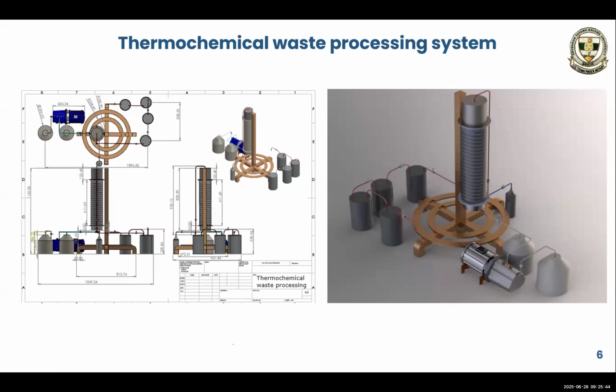hot demineralization, where with this system we charge in the water to demineralize the torrefied biomass while it is still red hot. The inorganic material that normally results in the formation of ash is already excited, and by the time you add water to it, it's quenched directly and leached into the water. Then you've got water which is rich in alkaline metal, which can be utilized for lignin extraction. So this is a 2-in-1 reactor system that is able to solve our problem.